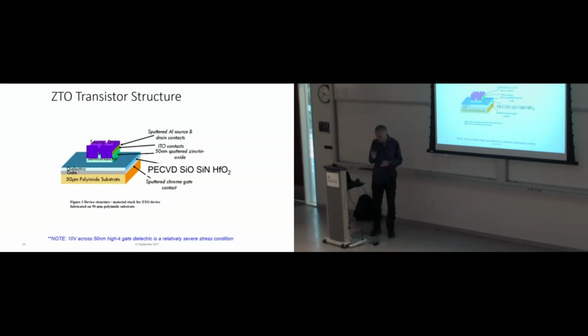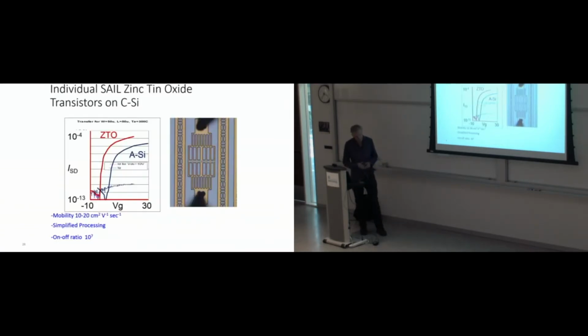Now, we've also done it with zinc tin oxide, so metal oxides. It does require working out the chemistry a little bit. But this one we had ITO contacts and zinc tin oxide. HP actually has a lot of intellectual property in the metal oxides. We filed a patent at the same time Hosono filed, and somehow ours got granted and his didn't, which is amazing. It was partly through Oregon State, and with hafnium oxide dielectrics. We made those kinds of transistors, and of course, they're way better than amorphous silicon. You can see that the amount of current is quite a bit higher.